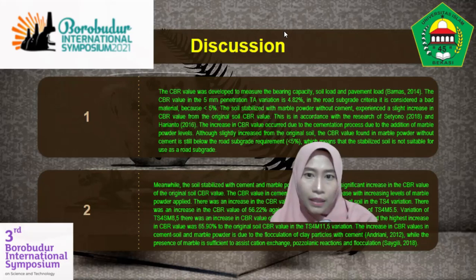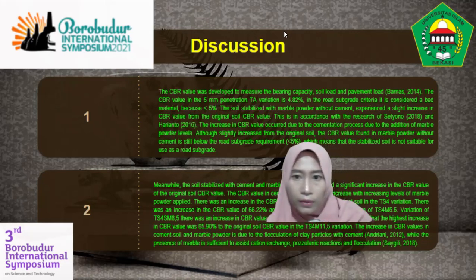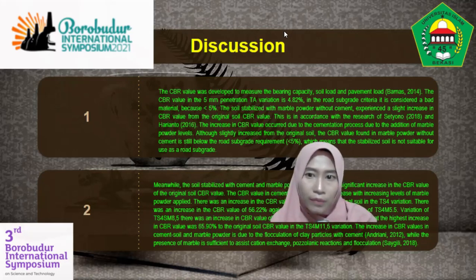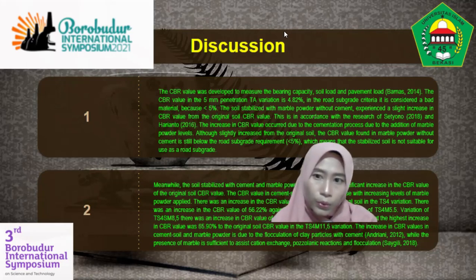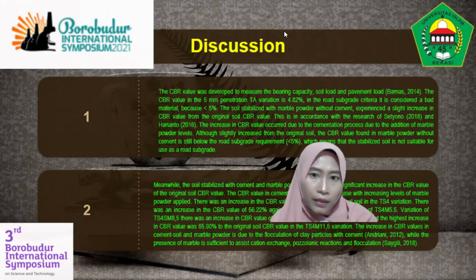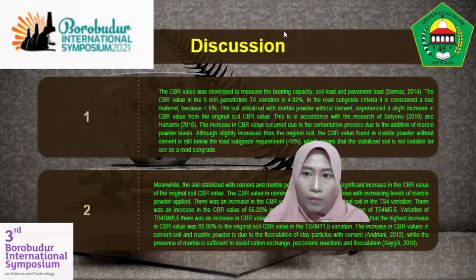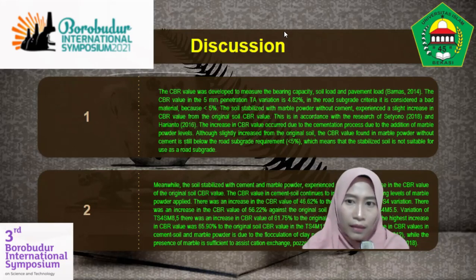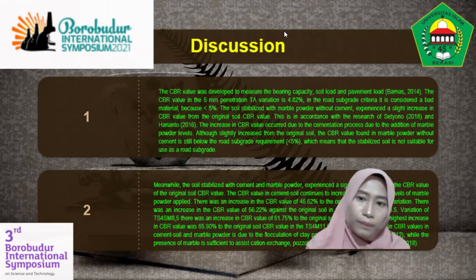The increase in CBR value occurred due to the cementation process due to the addition of marble powder levels. Although slightly increased from the original soil, the CBR value found in marble powder without cement is still below the road subgrade requirement of under 5%, which means that the stabilized soil is not suitable for use as a road subgrade.